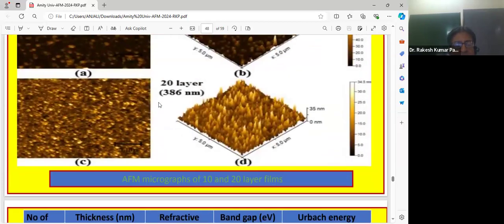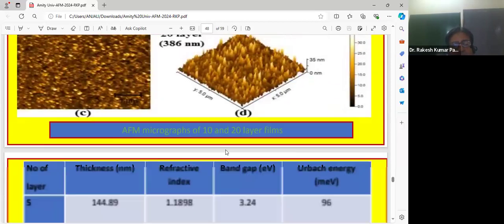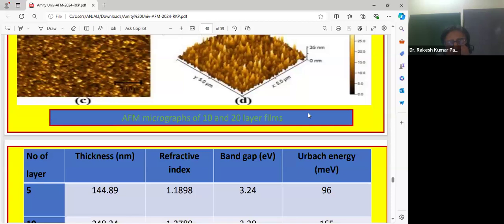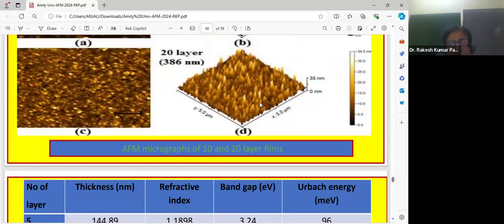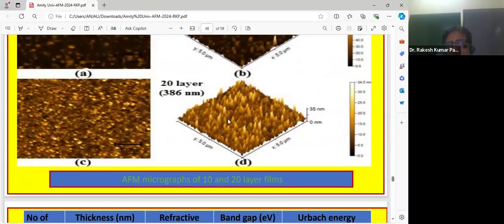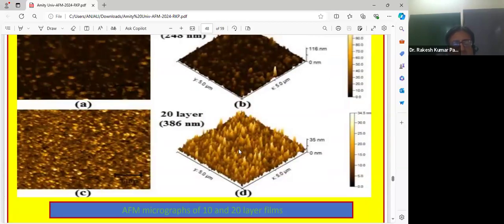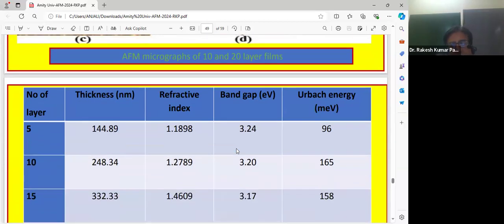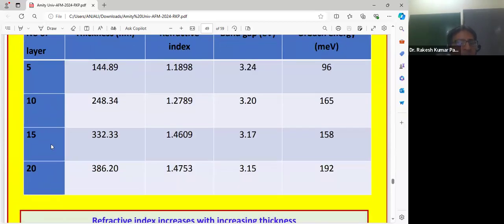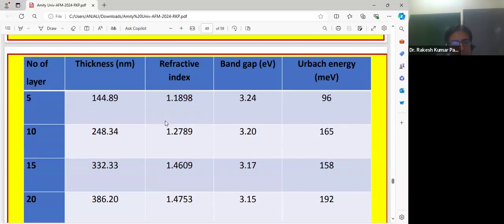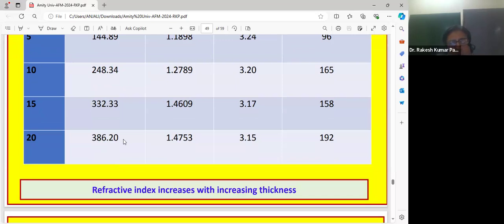This is another set of AFM images, 2-dimensional and 3-dimensional, of 10 layer and 20 layer aluminum doped zinc oxide film. Now you see the surface roughness and all these can be easily calculated, measured and observed by using AFM techniques. We have synthesized some aluminum doped zinc oxide thin films. This table indicates how the thickness, refractive index, energy band gap and Urbach energy are a function of thickness. Thickness is measured in terms of number of layers. See how the thickness has increased from 144.89 nanometer to 386.20 nanometer, and accordingly its refractive index and energy band gap has decreased.